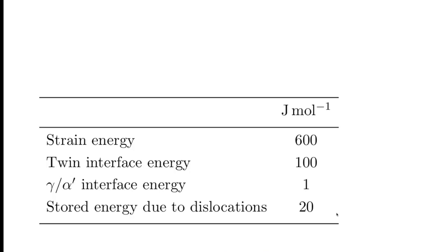That is just wrong. It only happens in certain cases where the martensite forms at a high temperature, and therefore the austenite cannot sustain the large shape deformation, and therefore it relaxes plastically, and those dislocations are absorbed as the martensite plate thickens. But these two terms are not independent. You know, if you relax the shape deformation by plasticity, then this component decreases. Okay, so it's very important to realize that martensite does not always contain dislocations.